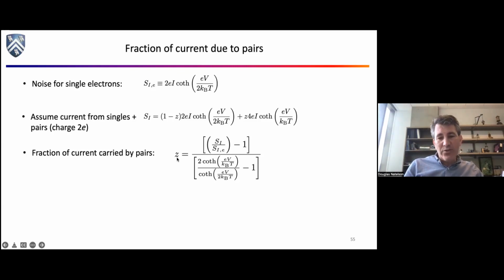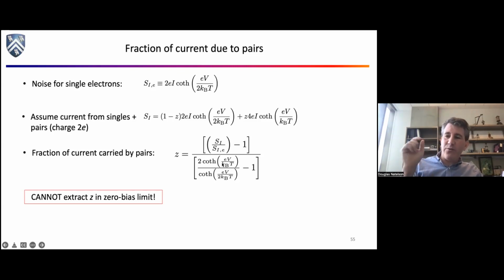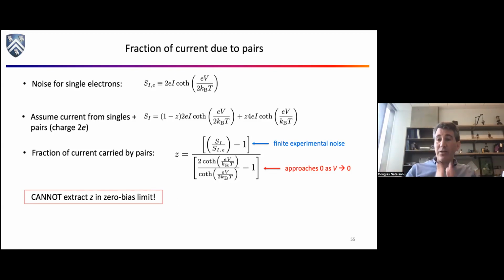Now you have to be careful when you do that, because if you go to the zero bias limit, down to very low voltages, the denominator of this thing goes to zero. So you can't really do this calculation, because you're sort of dividing by zero. And that's fine, because like I said at the very beginning, if you're in equilibrium, if you're not driving the thing at all, what you should get is the Johnson-Nyquist noise.